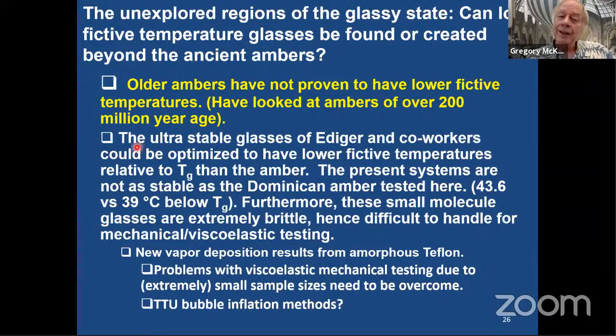So we thought, oh, the ultra-stable glasses that Mark Ediger has made and that Ken showed a little bit of in the end of his talk, could they be optimized to have lower fictive temperatures relative to TG than the amber? So the present systems are not as stable as the Dominican amber tested here. So we got 43.6 degrees below TG, whereas Mark's record was 39 degrees or so below TG. The other thing is these small molecule glasses are extremely brittle, so they're difficult to handle for measuring the dynamics, at least using what I use, which is rheology or mechanical testing.